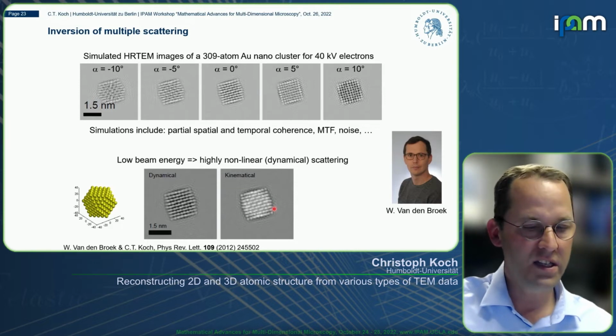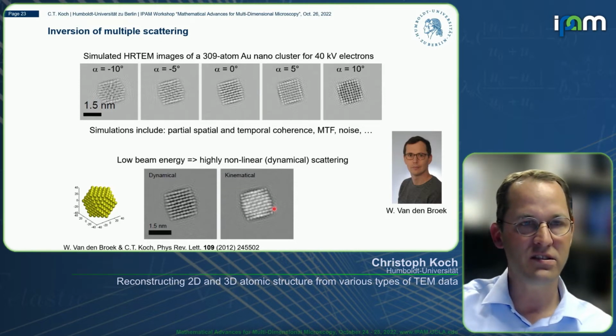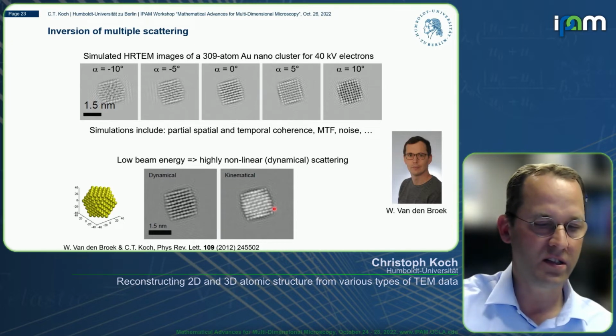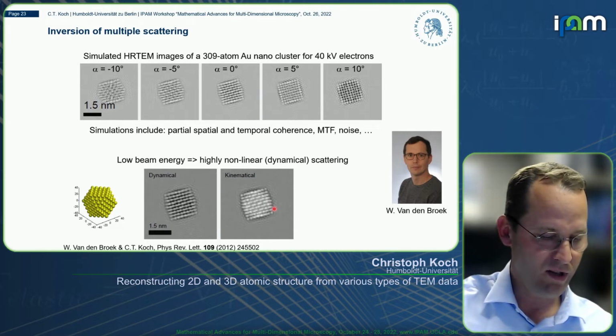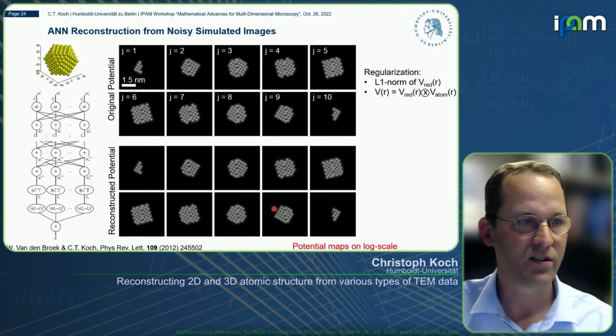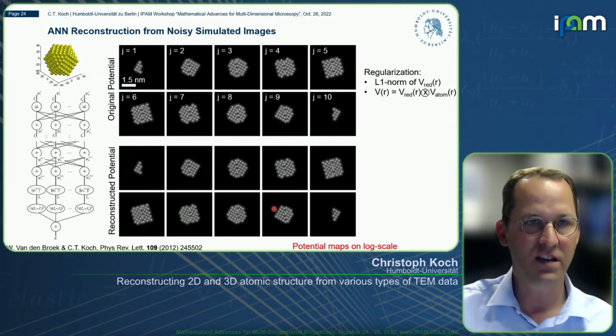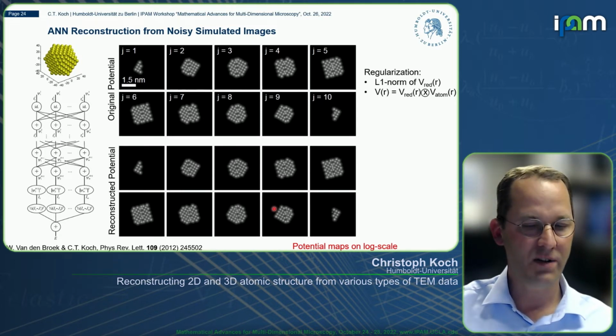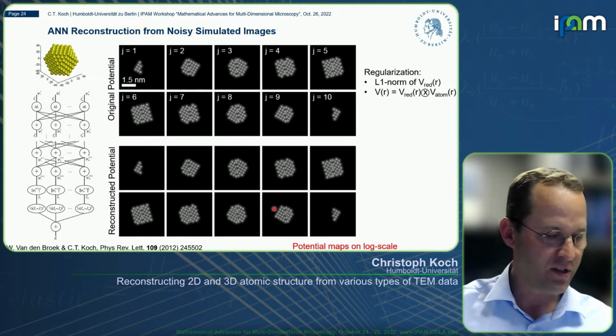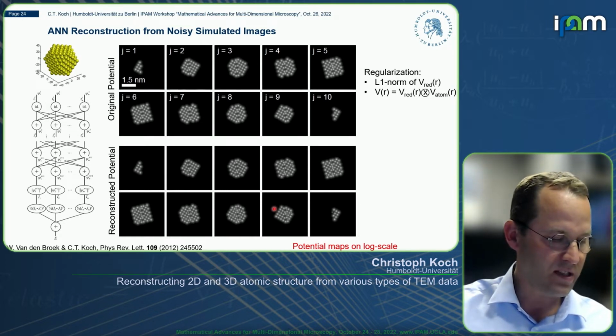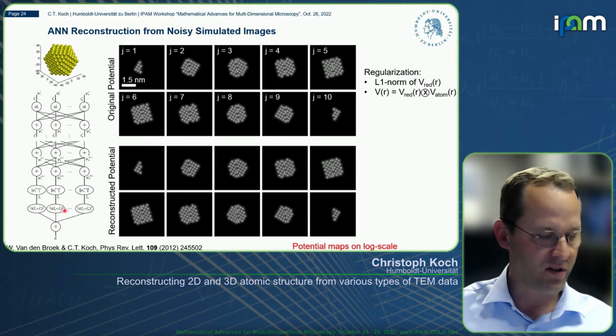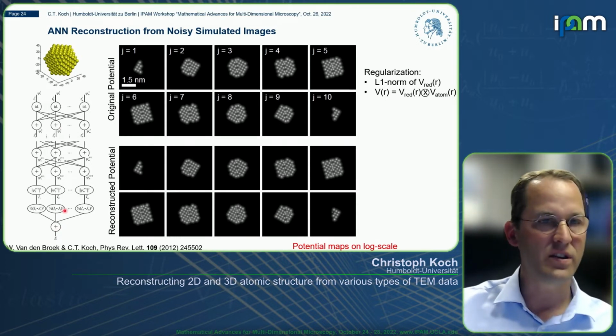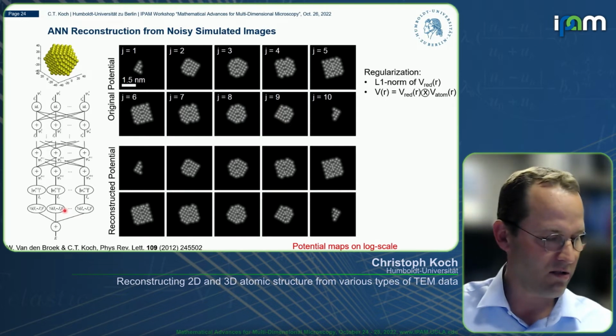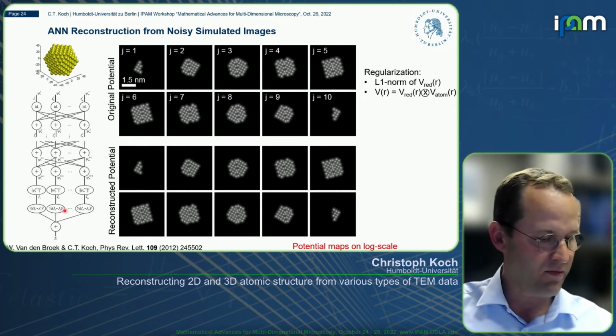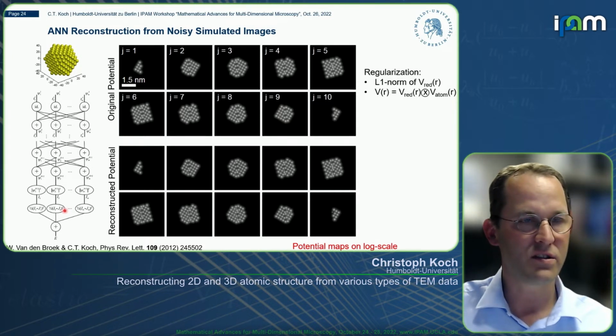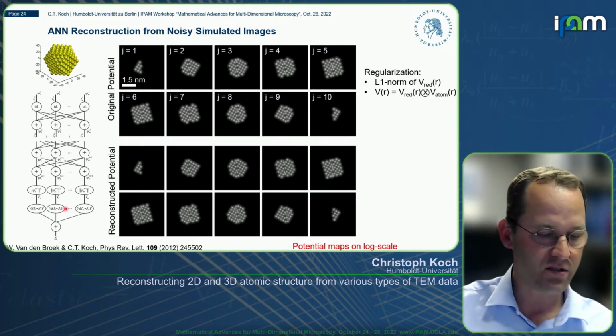So this is all in simulation only, and Colin talked about this yesterday, that this is really tough to do if you want to do this experimentally. So I admit we also haven't really continued trying to do this experimentally yet, because ptychography, as Colin said, is actually quite powerful and contains even more information. But just to show, this is the approach that we took, basically a neural network approach with a linear activation function. So I guess you shouldn't be calling it an artificial neural network, but the structure corresponds very nicely to the multiple scattering, and it then reconstructs the potential.